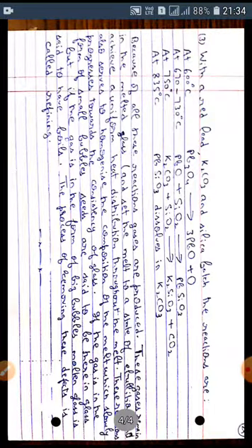Now the third possible condition is a third type of batch material, which is used if it uses red lead, potassium carbonate and silica batch. The reactions occur at 600 degrees centigrade. The first reaction occurs and Pb3O4 decomposes into lead oxide and oxygen. At a temperature range of 670 to 730 degrees centigrade, lead oxide reacts with silicon oxide to form lead silicate PbSiO3. At a temperature of 750 degrees centigrade, potassium carbonate reacts with silicon oxide to form potassium silicate and gives out carbon dioxide. At a temperature of 835 degrees centigrade, this lead silicate dissolves in potassium carbonate.